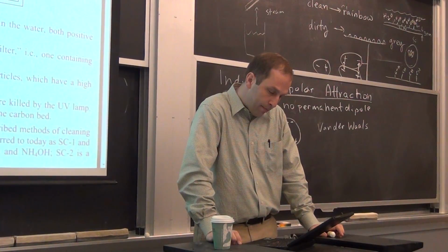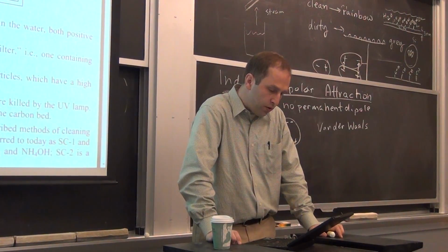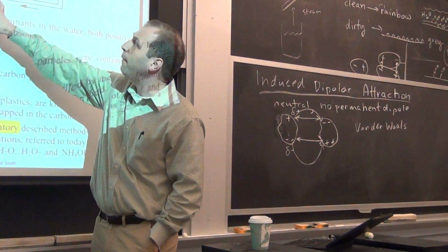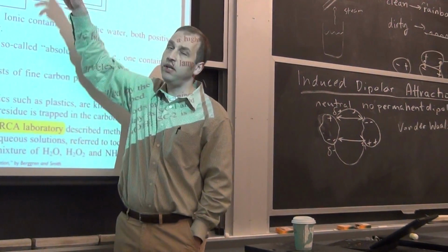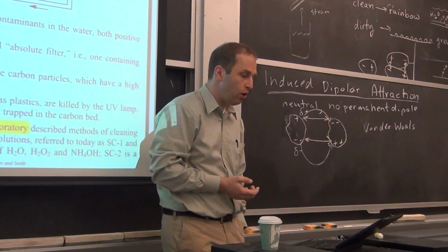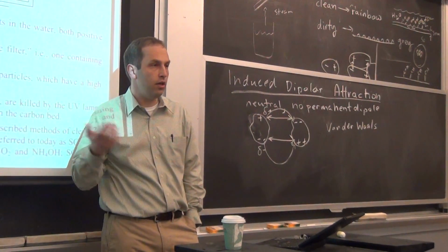Okay, so water is very often used to remove contaminations. There's a whole procedure I won't go into here for making deionized water. Basically, it's a process of killing the bacteria, removing minerals, and then physically filtering the sort of dead carcasses of the bacteria and whatever else out of it. And then you measure the resistivity, and if the resistivity is above 18 megaohms, then it's considered deionized, and then you can use it in your rinse tank to rinse your wafer.